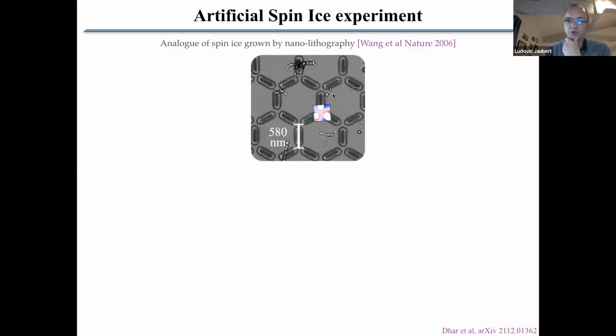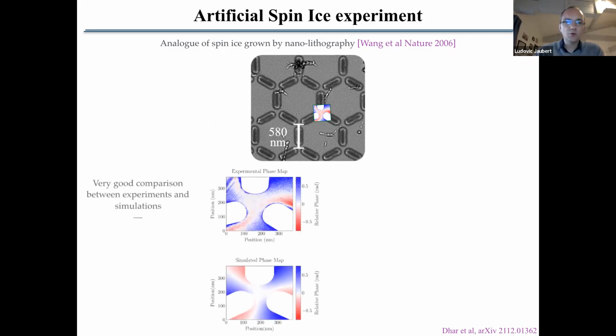So coming back to the question that I had at the beginning of this seminar. We asked colleagues to grow this artificial spin ice, and then we measured the electron holography via TEM, transmission electron microscopy. We measured it, and as you can see here, this is experimental data, and this is the theoretical curve. And we have a very good match between the experimental phase map and the simulated phase map.